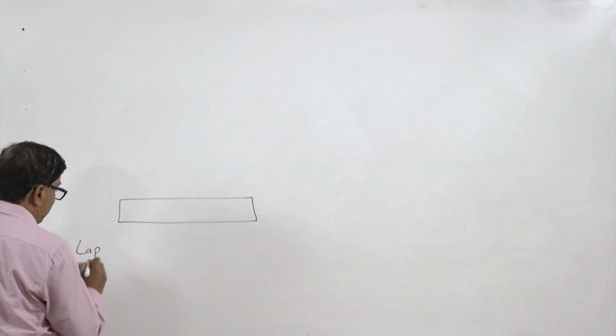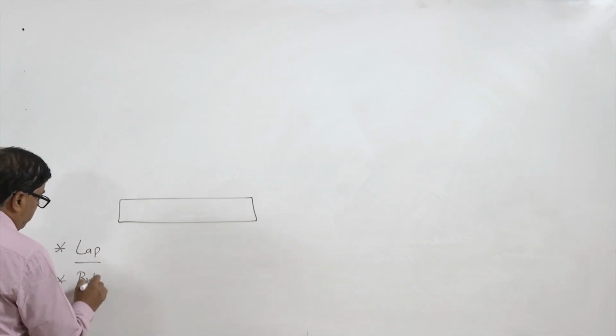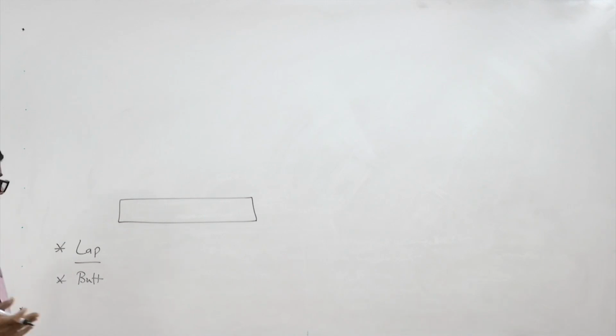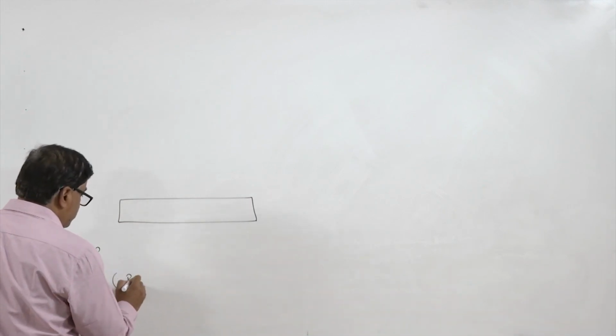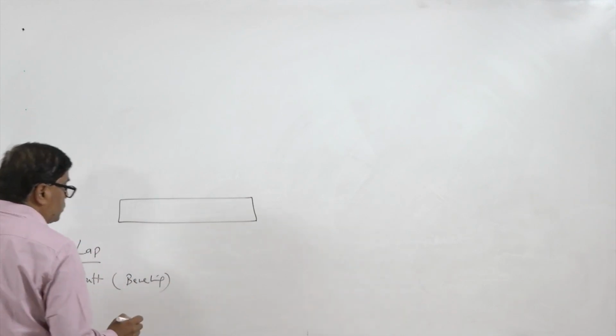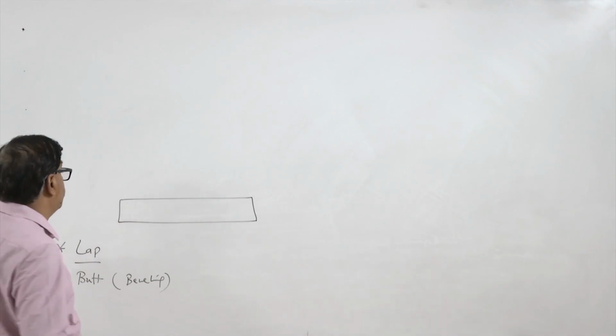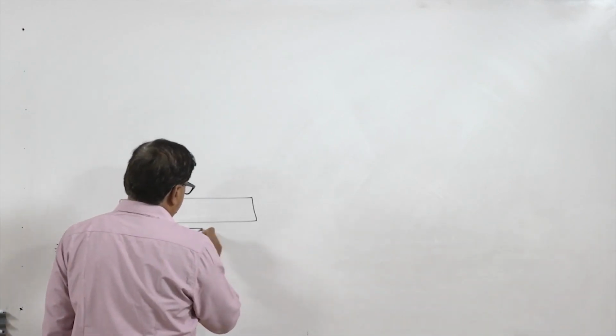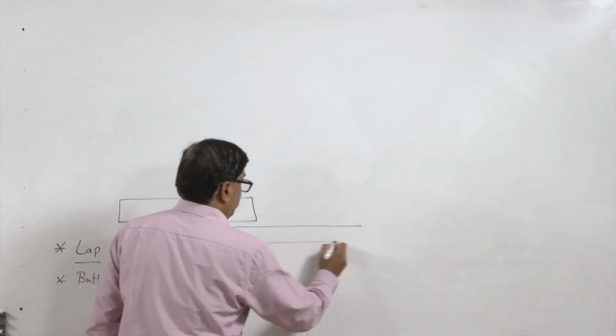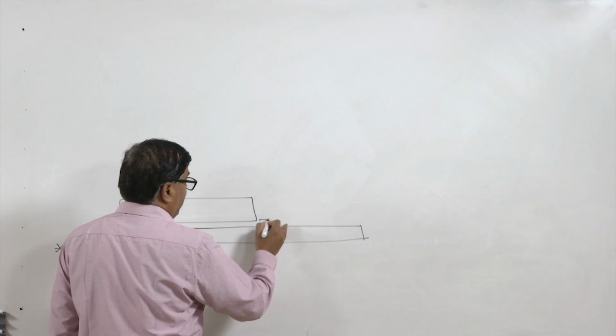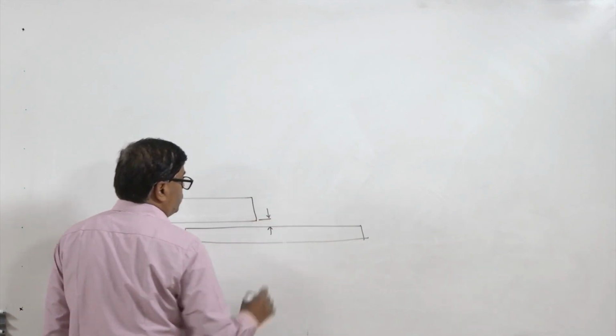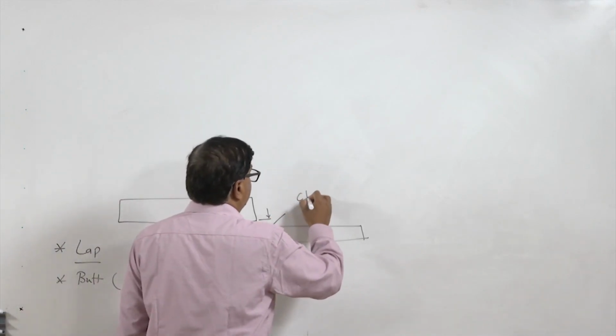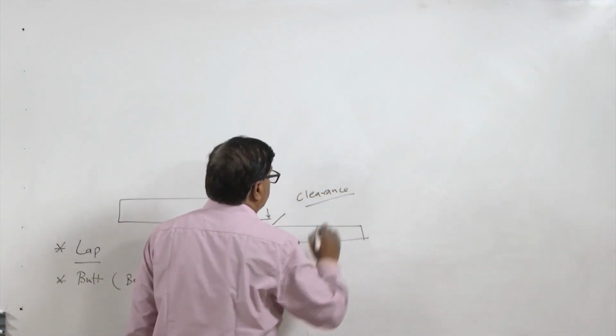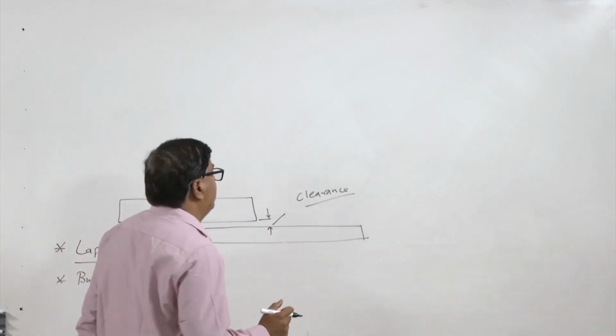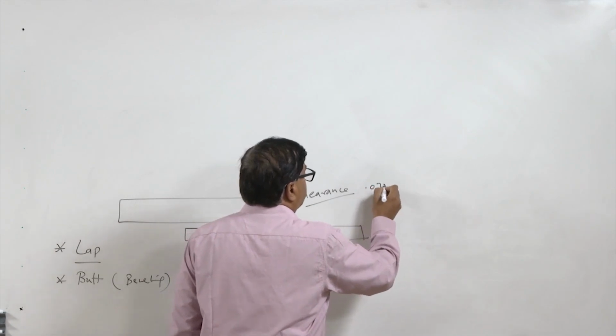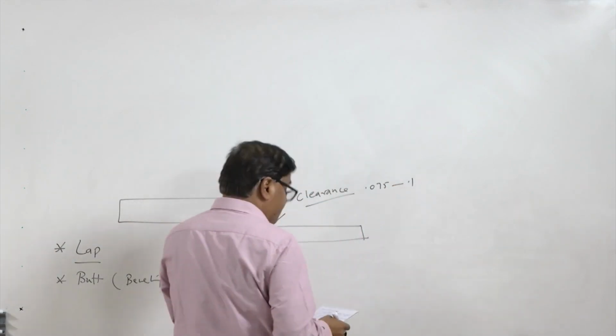The most common one is the lap joint configuration, and sometimes even a butt joint can be made for those cases, but for making the butt joint, beveling is especially tried so that the required joint strength can be achieved. As far as the lap joint is concerned, the plates or the sheets to be joined are kept in lap joint configuration, and a particular gap between the plates and the sheets to be joined is maintained, which is called clearance. This clearance plays a very big role for successful brazing and soldering, and this is kept like 0.075 to 0.125 mm.